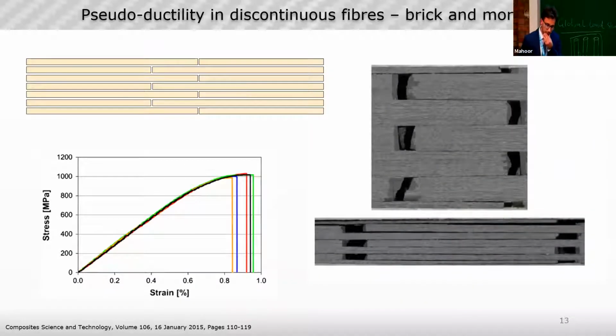Another strategy for generating pseudo-ductility is not based on the fracture of the fibers, but on delamination. So strategically designing the layup to give us the possibility to gradually delaminate the material. In this case, the configuration is called brick and mortar. It's possible to also generate this kind of deviation. The approaches for pseudo-ductility based on delamination allow us to generate this very smooth transition, which could be a little bit harder to generate with fragmentation or fracture of the material.